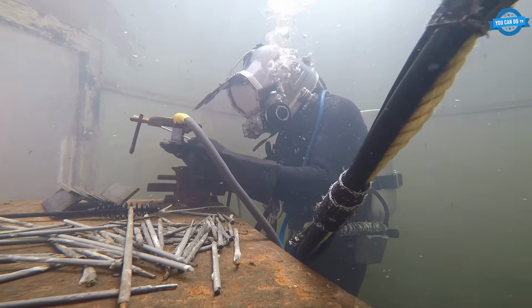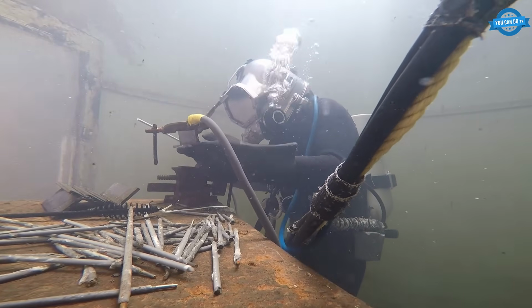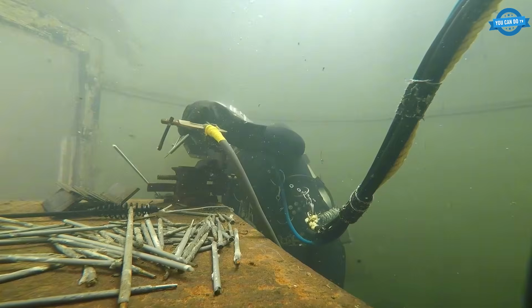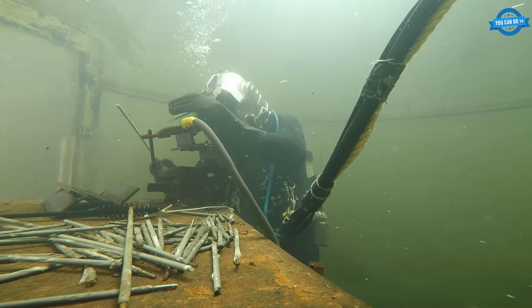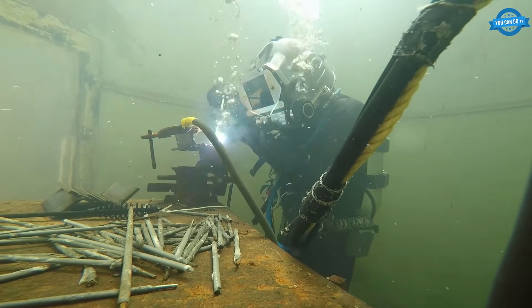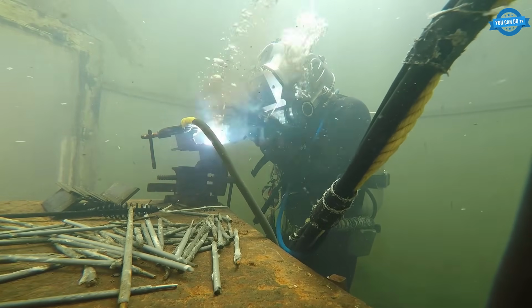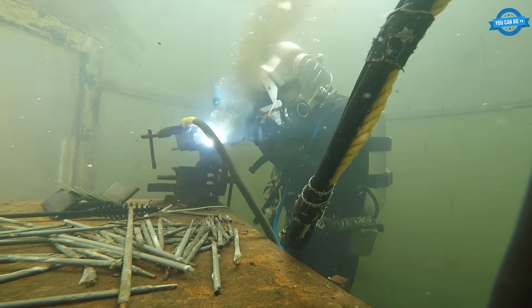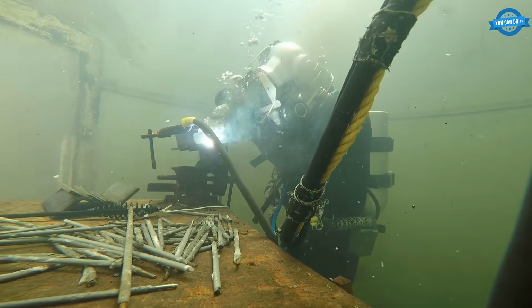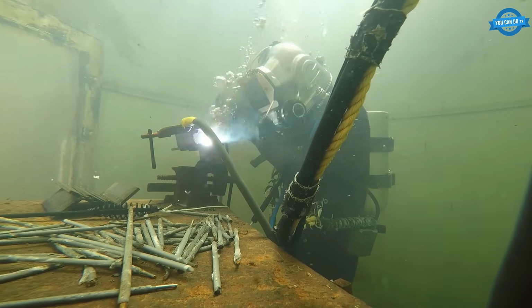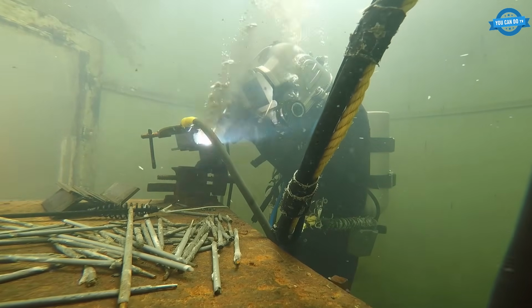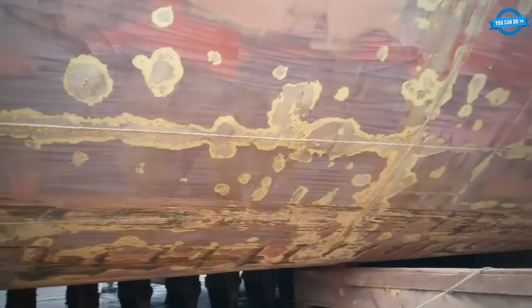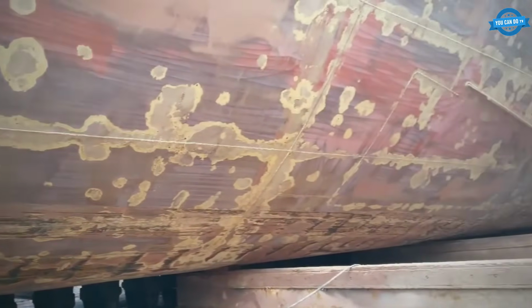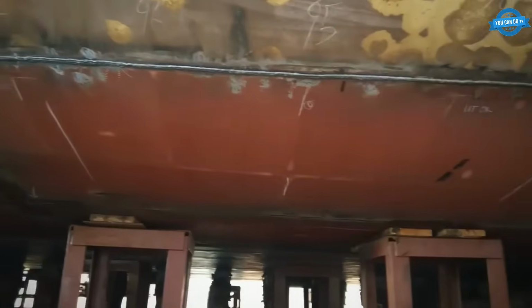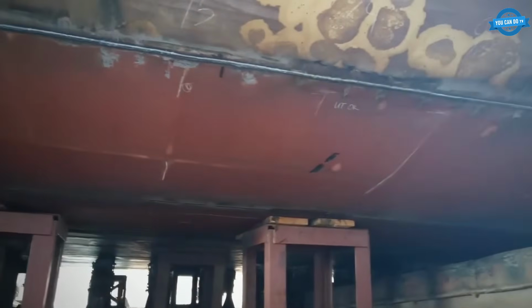After a pass, the diver taps the weld to listen and inspects the structural build by hand. The torch is moved, the angle changed, and the next pass goes down. A weld put together this way carries the same problem every wet repair carries. What looks sound on the outside may not be sound on the inside. The inspector is not looking for damage that already happened. He is hunting for the spot where future damage could start.